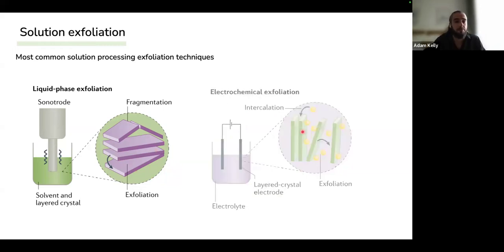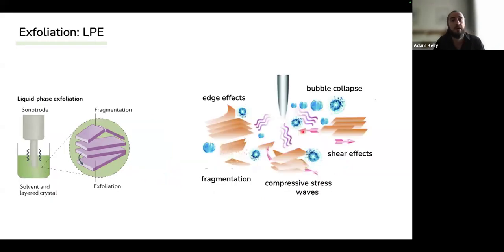So I'm going to speak about this one first, which is the one that I spent most of my PhD working on. So we take a sonotrode or a sonic probe. We take some solvent. IPA, for example, works. Water also with surfactant. And we take our layered crystal, our powder, and we put it in at a certain concentration. And then once you turn on this sonotrode, we get all these effects that go on.